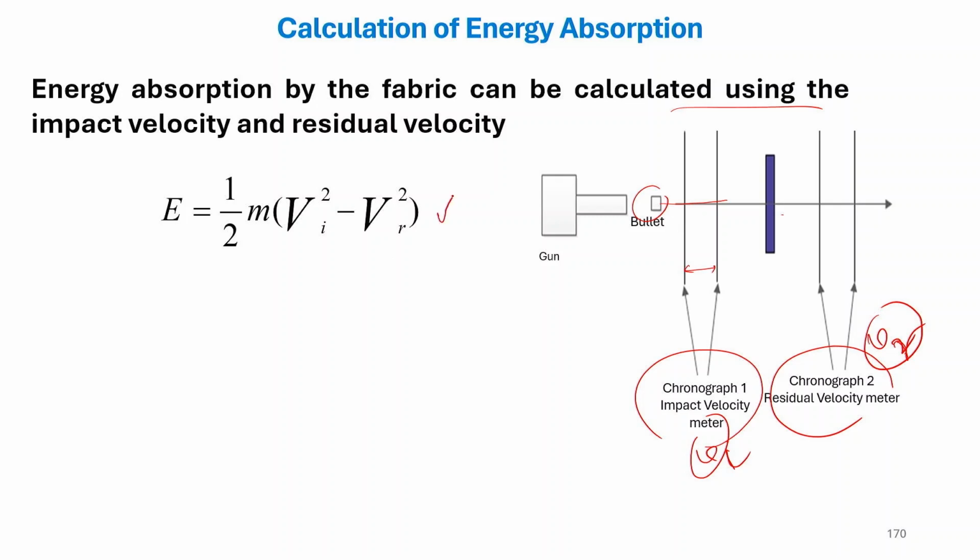So, from there we can calculate the energy absorption, but in this test our idea is that the speed should be such that it penetrates through this material. If it does not penetrate, this energy absorption method will not be valid.